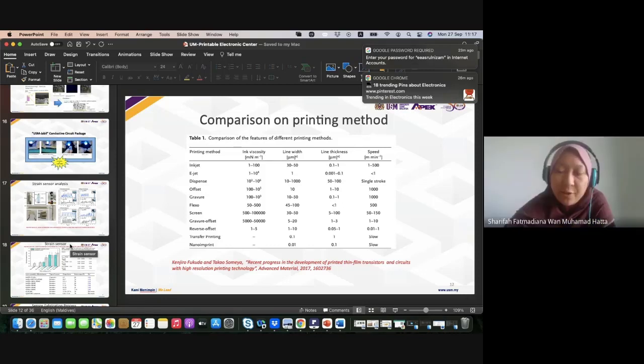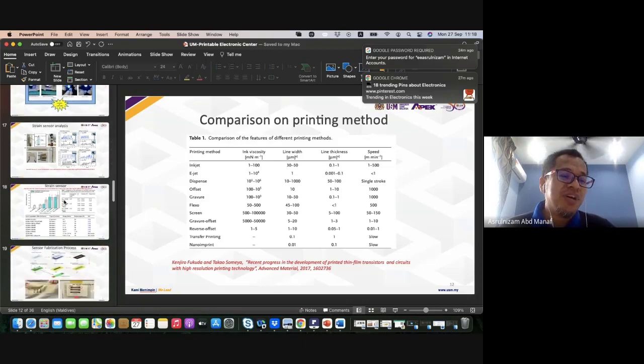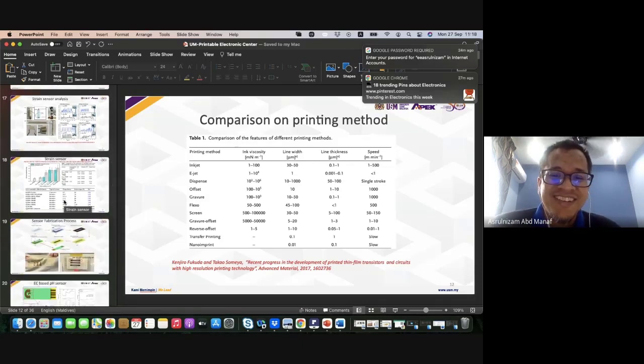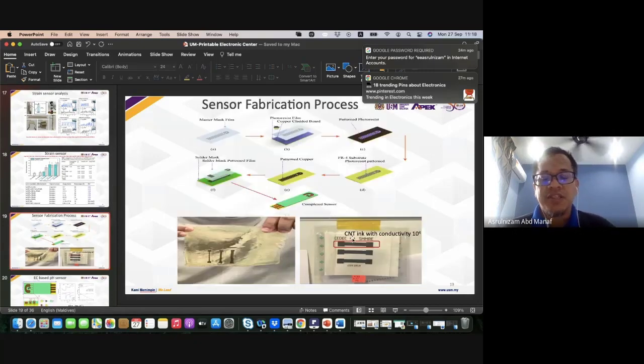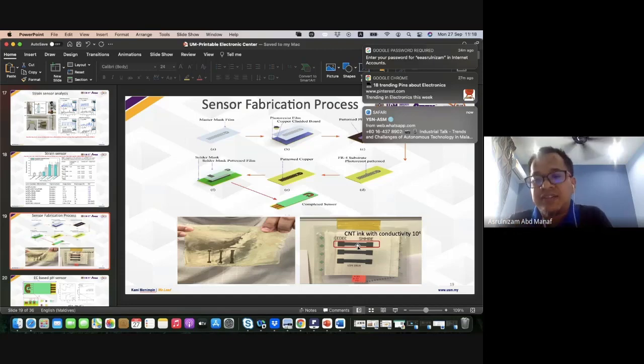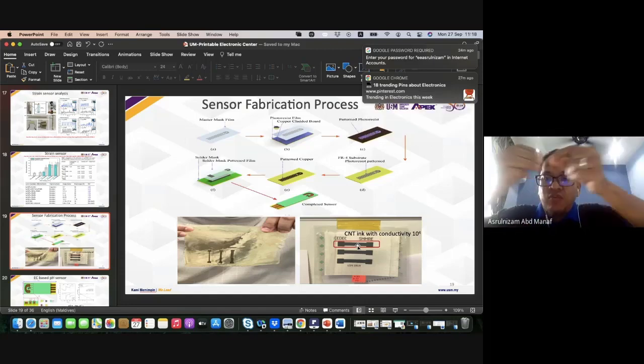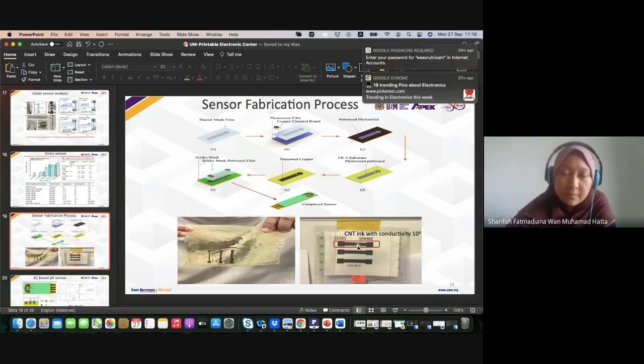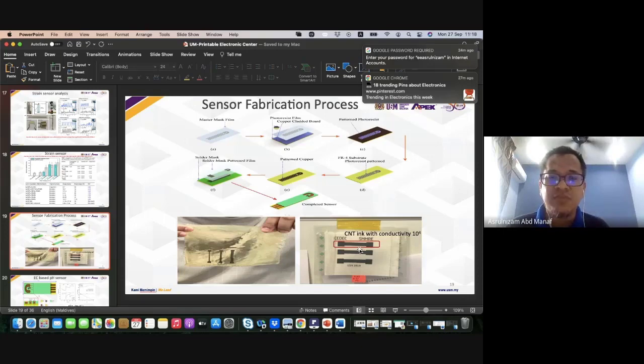Okay. And then for your smart bandage, you directly printed on the cotton bandage, is that right? Yeah. Any specific issues you face when printing on textile? Of course. The first is connectivity. Because when you have cotton, a single layer should give connectivity, but no, we need multiple layers. One layer is still not enough. That's why in some cases we do about 20 layers.